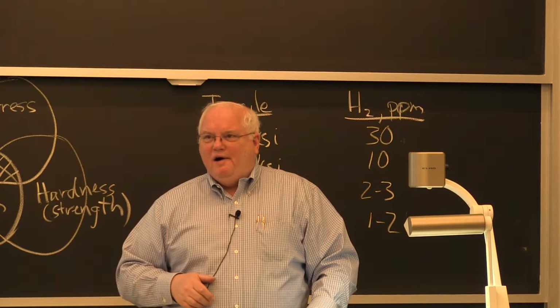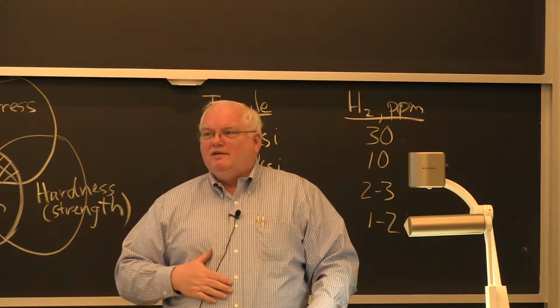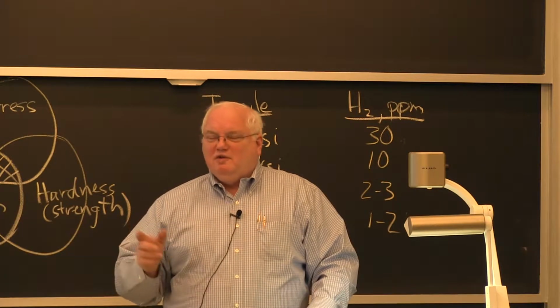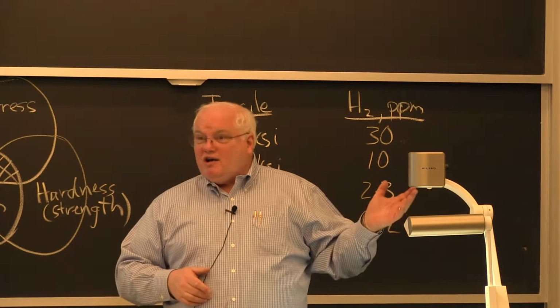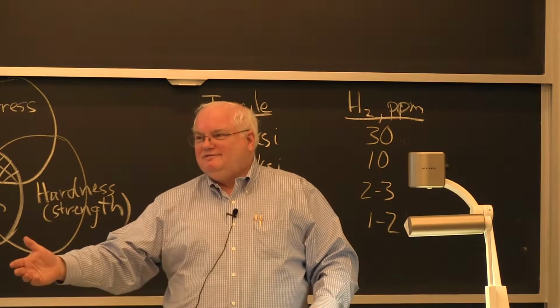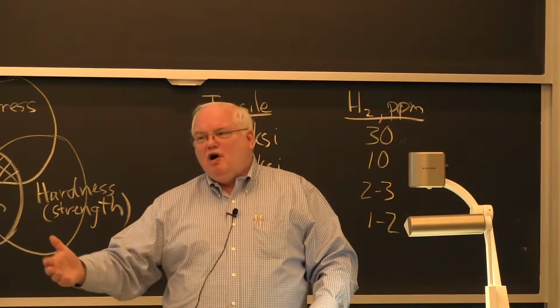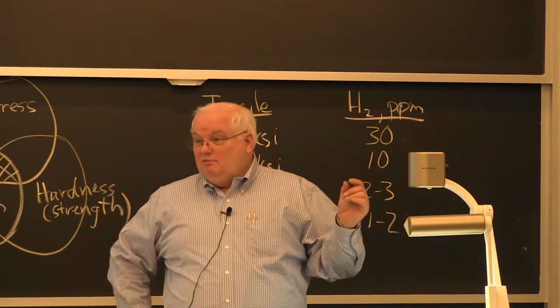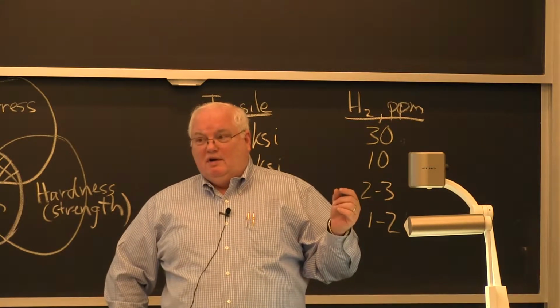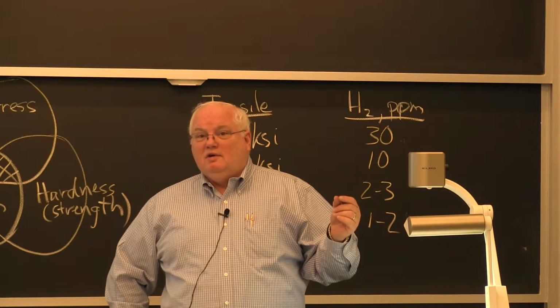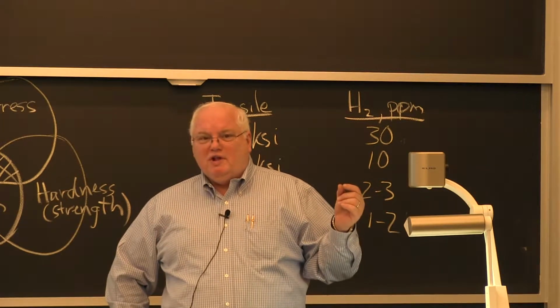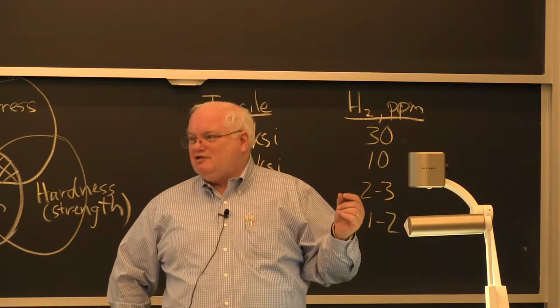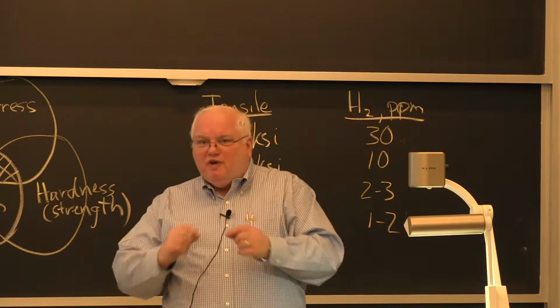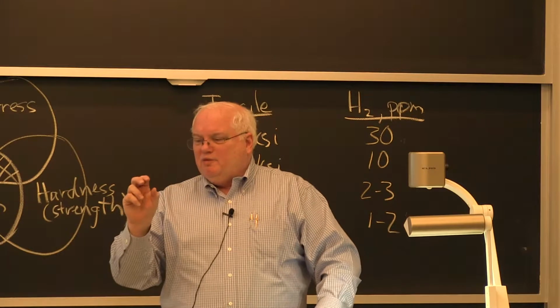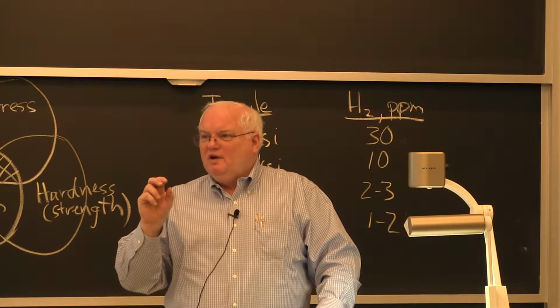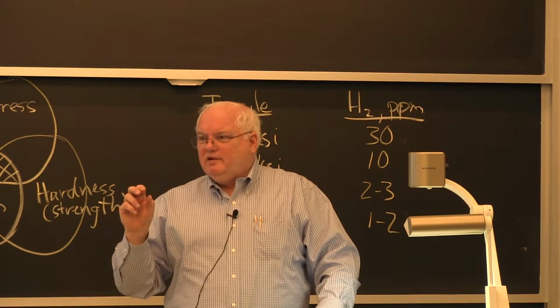Well, we can do either one. Okay, I'll tell you, the secret is it's the biggest part and it's the smallest part. If you go to shipbuilding, you've got to hold a quarter of an inch over 100 yards. Start figuring that out. It's about 1 part in 20 or 30,000. It's much finer than some guy trying to mill or machine a bar to 1 inch plus or minus 10 thousandths of an inch.